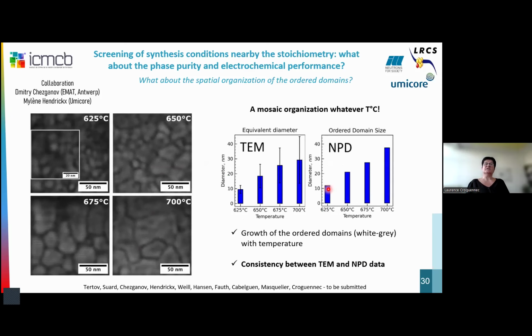And I spoke about this effect of temperature. When the annealing is performed at 625 degrees and moving to 700 degrees, you can see that we have exactly the same mosaic effect, whatever the temperature. And you can see that we increase the size of these ordered domains from roughly 10 nanometers to 30 nanometers here.